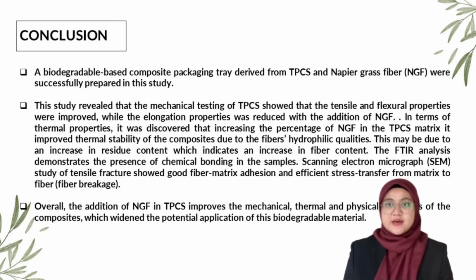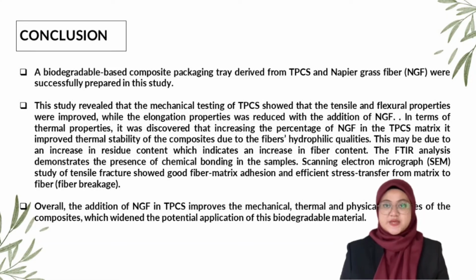At the end of this study, a biodegradable-based composite packaging tray derived from TPCS and Napier grass fiber was successfully prepared. The study also revealed that the mechanical testing of TPCS showed that the tensile and flexural properties were improved, while the elongation was reduced with the addition of Napier grass fiber. In terms of thermal properties, it was discovered that the increasing percentage of Napier grass fiber in the TPCS matrix improved the thermal stability of the composites due to the fiber's hydrophilic qualities. It might also be due to an increase in residue content, which indicates an increase in fiber content.